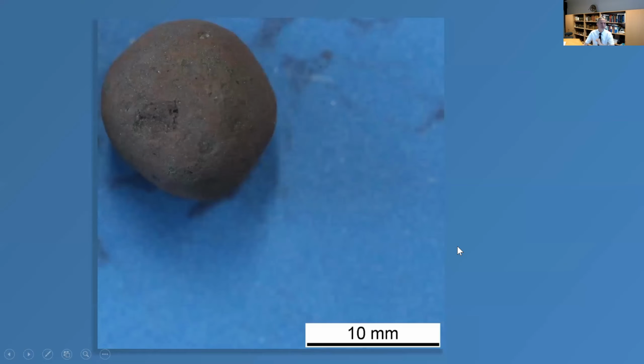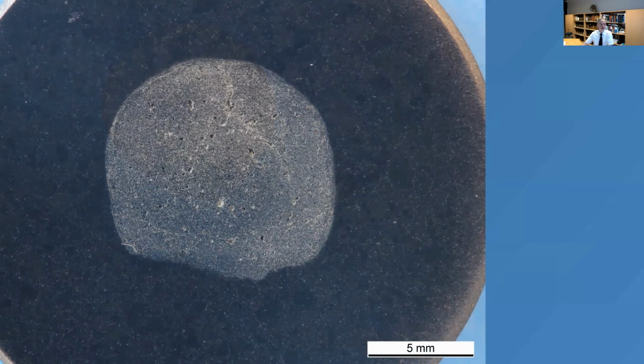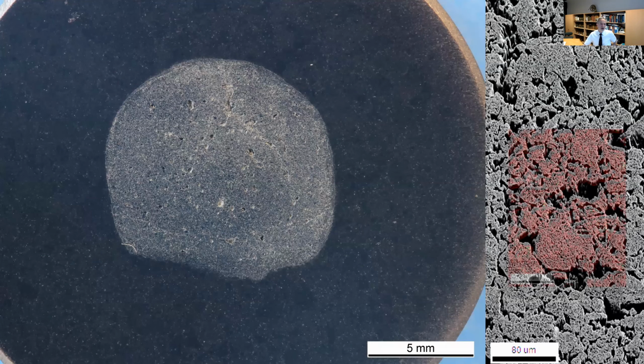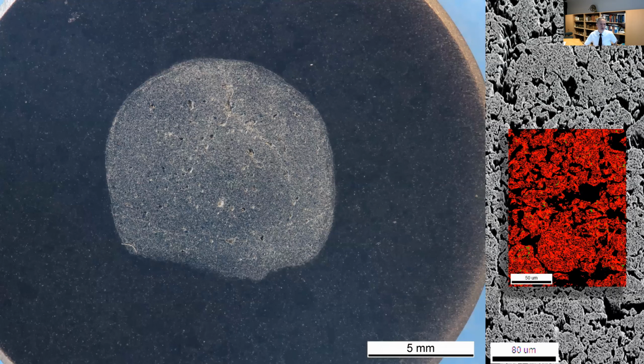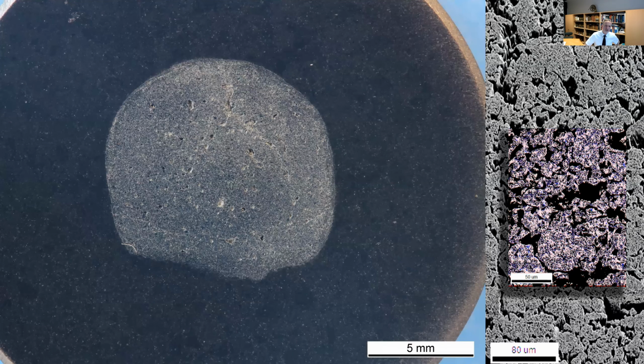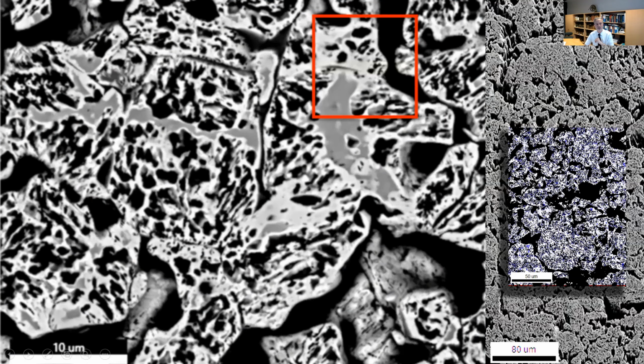Now let us fly a little bit through such a pellet, which is a product that is made from the ore. It's just baked together to carry an oven load. And when you cut it open, this is all work by my colleagues Jan Ma and Isnaldi Filho and a couple of other colleagues who work on that topic. And you subject it to electron microscopy probing, you see that this is a very nanoporous, a very fine structure. It looks, by the way, similar if you do that with a single crystal of wüstite. That means although the single crystal has such a high mass loss of oxygen and several phase transformation stages between these oxides before they finally turn into iron, you have a very complex array of porosity, nanoporosity, and fracture.